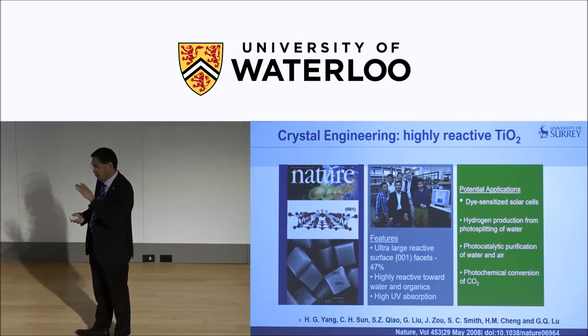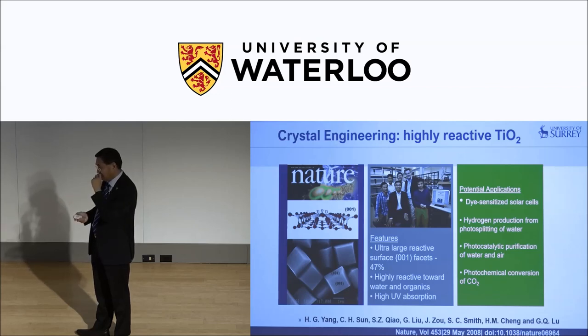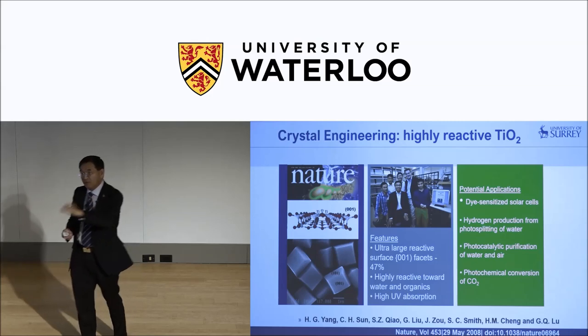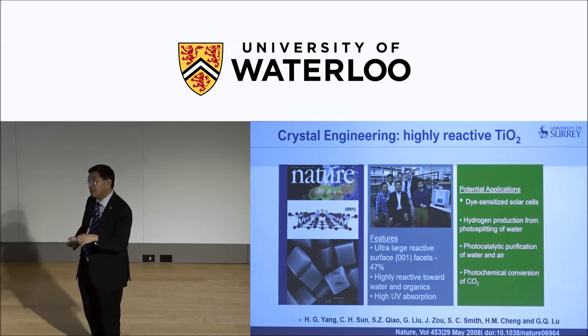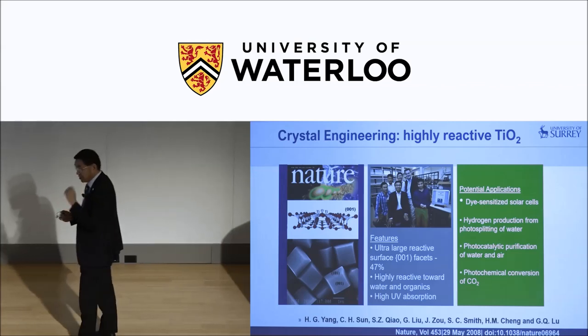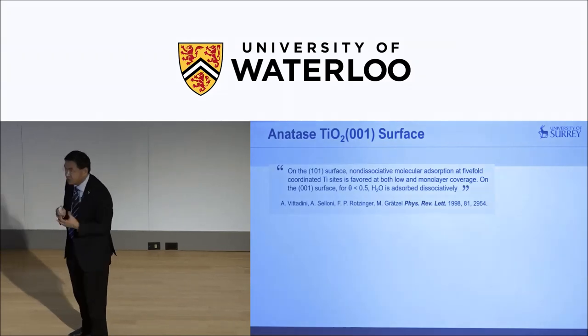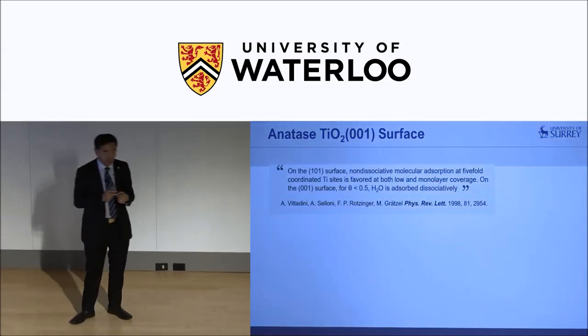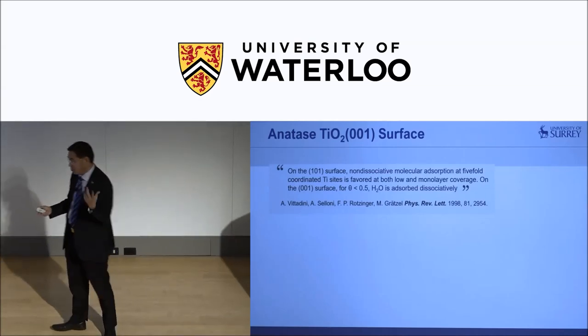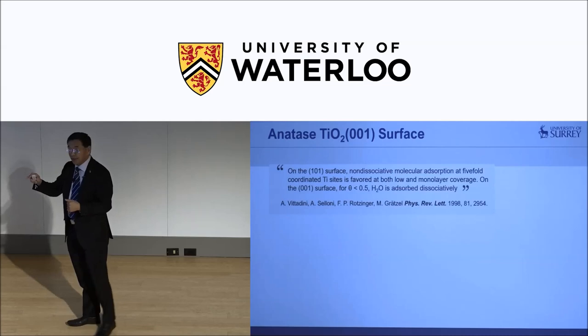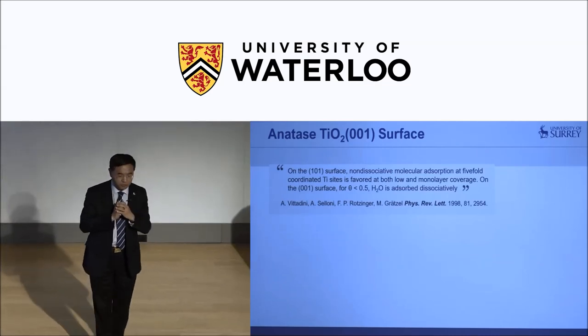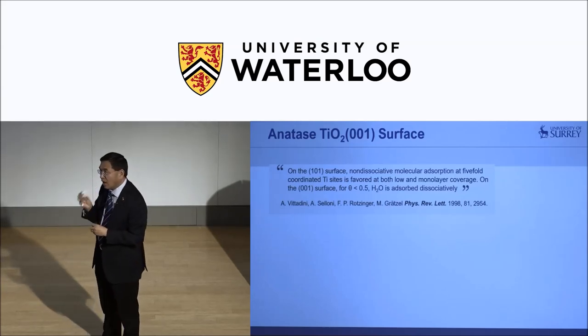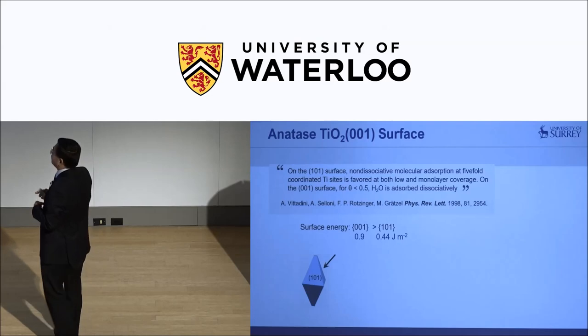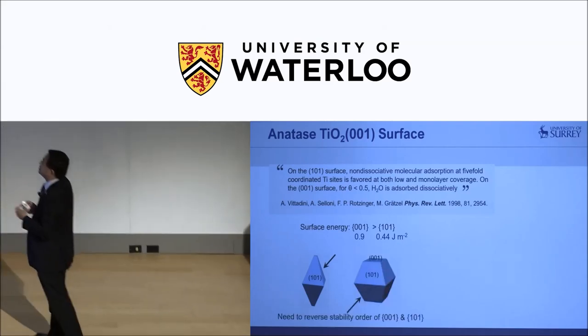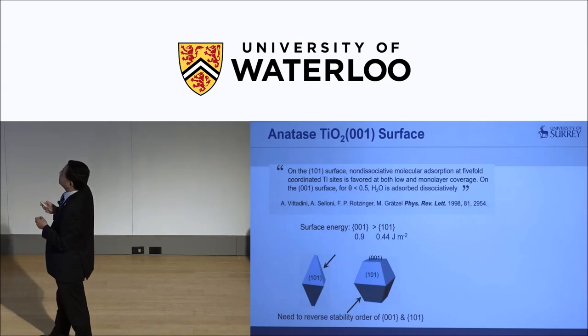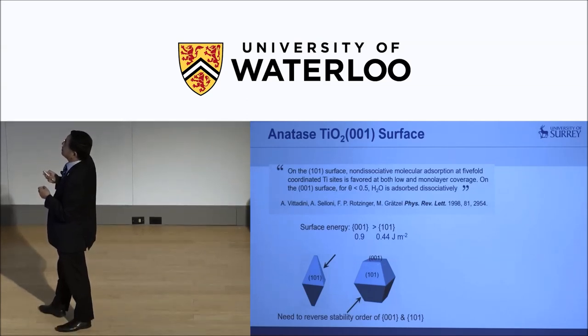We achieved, in the first work we did, published about 10 years ago, 47%. Later, there was a lot of improvement. We can get to 84-85% of 001, highly reactive facet, but a stable phase, and it has a lot of applications. It all started from the inspiration from Michael Grätzel's work. It's a theoretical work. Annabella Selloni and I was in Princeton, and they did this work published in 1998 to say that, well, in anatase crystals, you have two dominant phases, and one is actually highly energetic, and this is the most stable 101 phase, and this is the top one, truncated here, is the 001 phase. 001 phase has high energy.